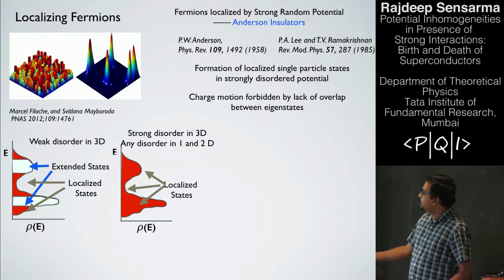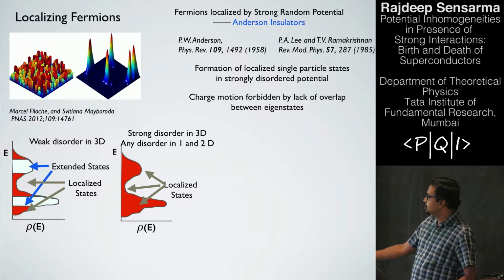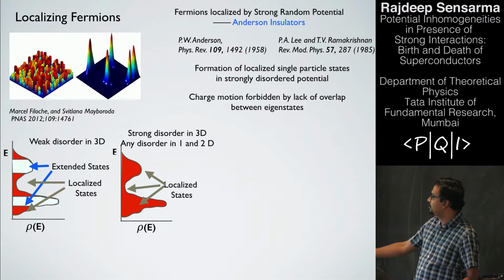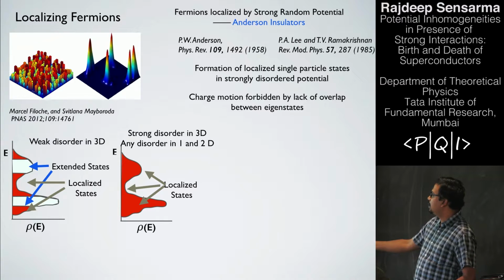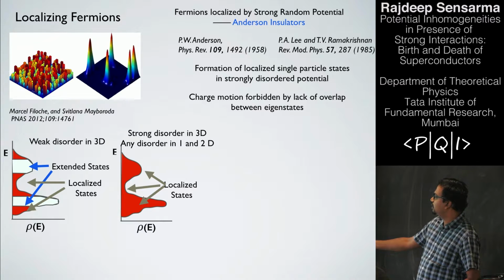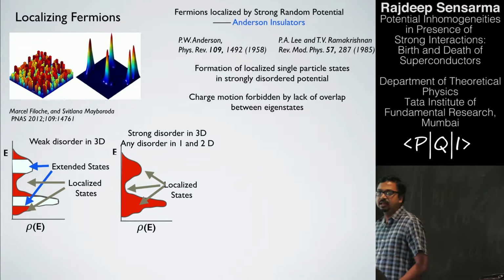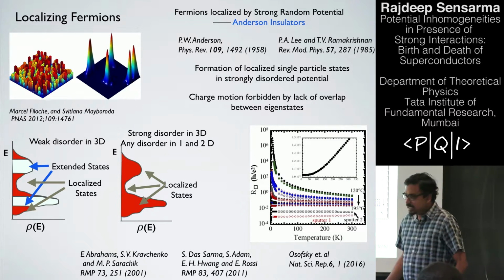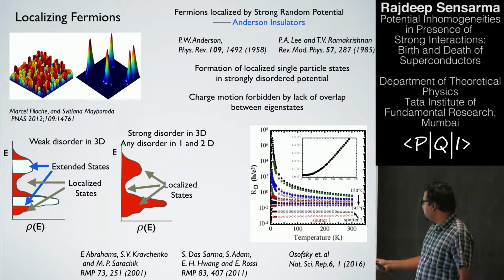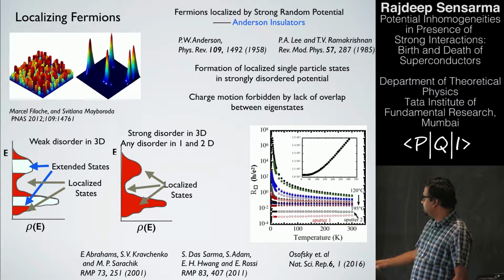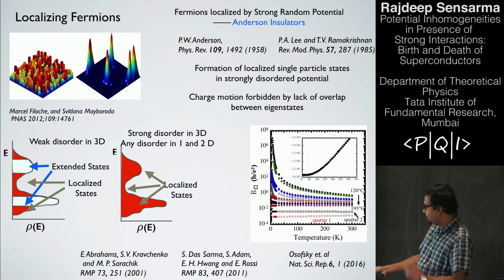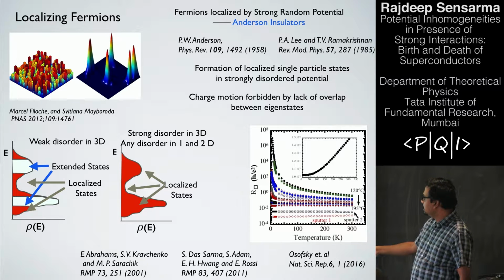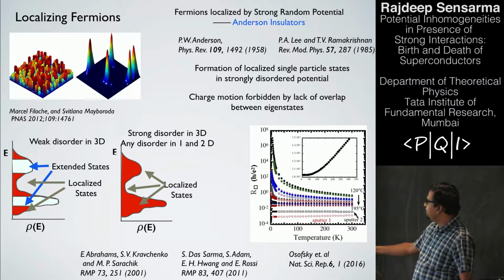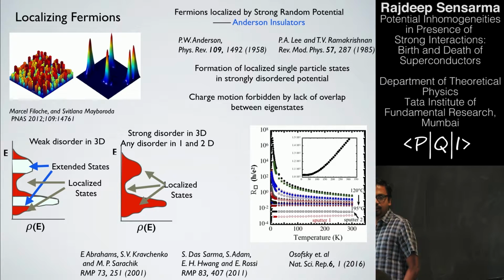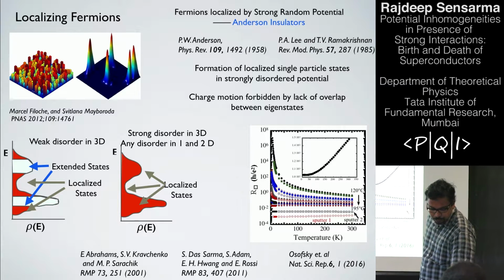In 3D, you will basically have localized states mixing with some extended states in between, whereas if you have strong disorder in 3D and any disorder in 1D and 2D, all states become localized for the fermions. And you can see something similar as you increase disorder. What you see here is very recent data where things start going from metallic to being insulators as you change the disorder strength in the system.